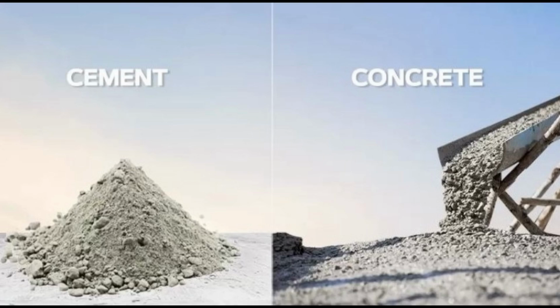Global warming potential, GWP, of GGBS decreased by 1.1 kilograms CO2 while FA decreased by 17.3 kilograms CO2 when the mineral admixture replacement ratio was increased by 10%. This study also compared the compressive strength properties of binary blended low-carbon concrete according to the replacement ratios, and the applicable range of mixing proportions was derived.